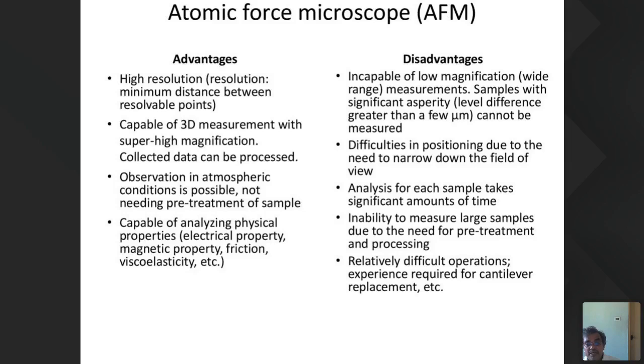The disadvantage is incapability of low magnification measurements. Samples with significant asperity cannot be measured. That means level differences greater than a few microns cannot be studied here. Difficulties in positioning due to the need to narrow down the field of view. Analysis for each sample takes a significant amount of time. Inability to measure large samples due to need for pre-treatment and processing. Relatively difficult operations. You need a trained, experienced operator, especially for the cantilever replacement, etc.